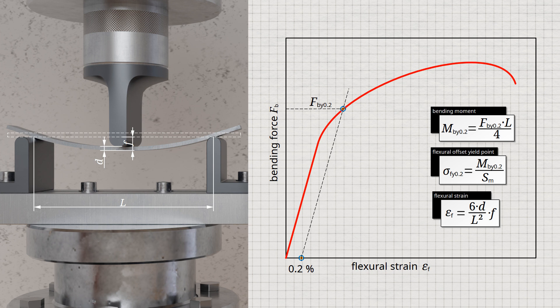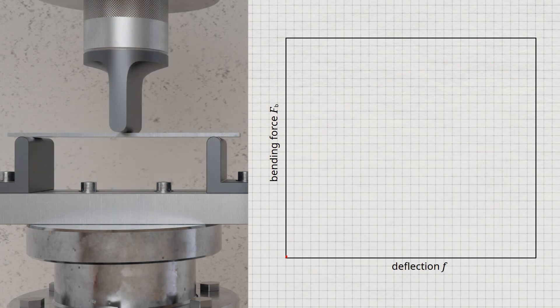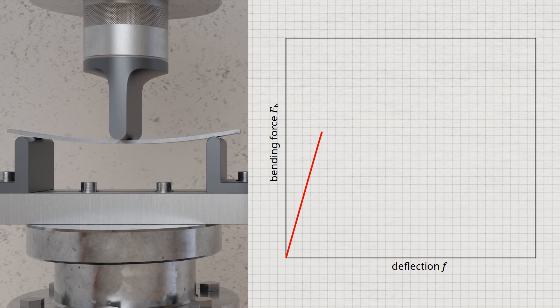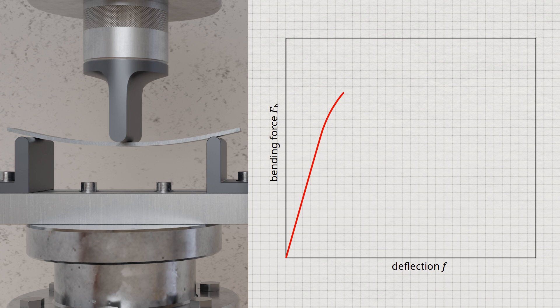With tough materials, the specimen can be plastically deformed beyond the flexural offset yield point as the load increases, but the specimen does not break — it would only be pulled through the two supporting pins. For tough materials, the flexural test is therefore terminated when the flexural yield point has been exceeded. Compared to ductile materials, brittle samples usually show a different behavior in flexural tests — the sample often breaks without any noticeable deformation. Determining a flexural yield point is difficult for such materials. Therefore, for brittle materials, it is not the onset of plastic deformation but the onset of fracture when the maximum bending moment Mb-max is reached that is used as the strength parameter.